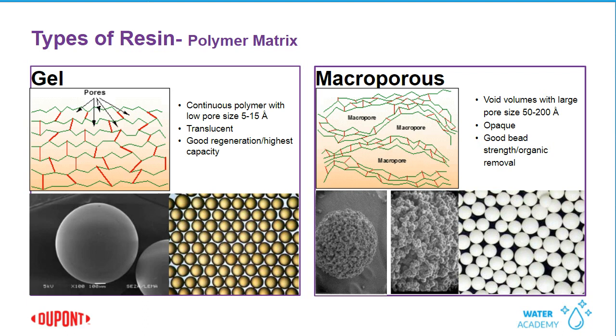On the other hand, there's the macroporous resin. This resin has a lot of porosity. If you look at the micrograph below, you can see a lot of nooks and crannies. There's a lot of surface area there. And we obtain this by using a compound called porogen that locks in void space, creating these macropores, which is excellent for removing large molecular weight compounds. Now, if you were to look at this under an optical microscope, you would see an opaque bead, and that is because these large pores diffract light.